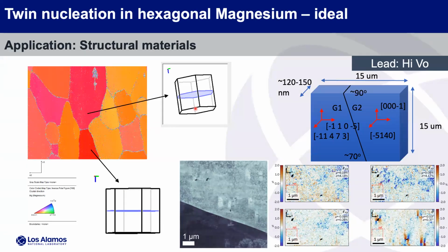So magnesium, an HCP crystal, is great for nucleating twins. We find a low angle grain boundary. This is electron backscatter diffraction. Take that grain boundary and cut out a FIB section of it. This is what it looks like here. This is what the strain state looks like at zero strain. These are magnesium oxide precipitates from which twins nucleate.